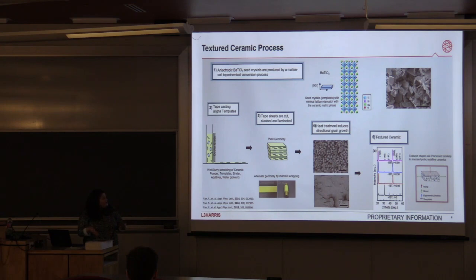When you choose a seed type crystal, you want to make sure that you have minimal lattice mismatch, close lattice constants, close structure. What I've shown up here is just the barium titanate structure, and what we're looking for is something that is highly anisotropic so that we can align it and engineer these domains in the next step. And this is just an SEM image of some barium titanate that we've grown that we call our seed or our template crystals, which are very important to getting this texture process.